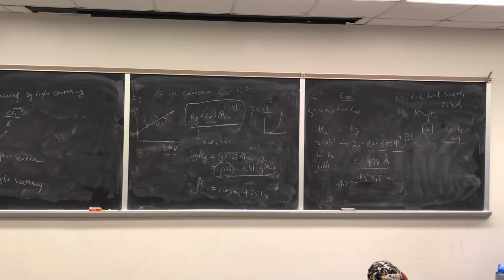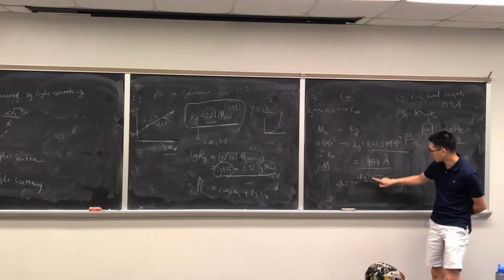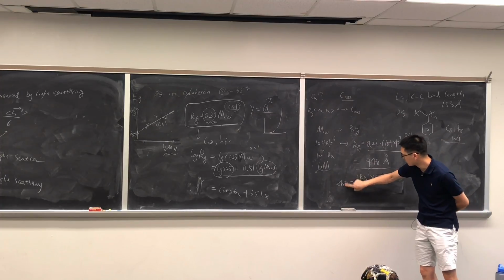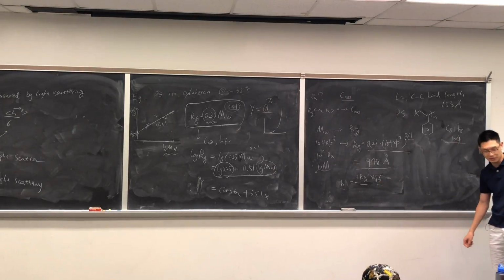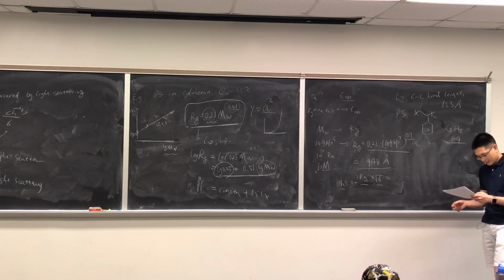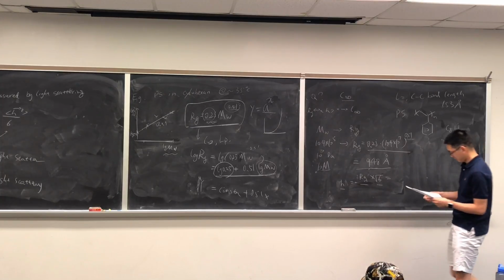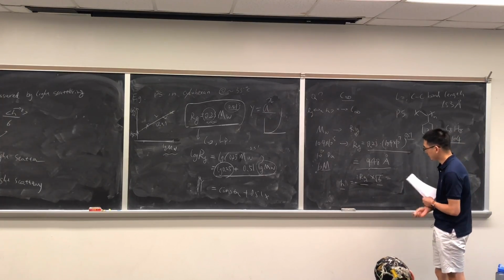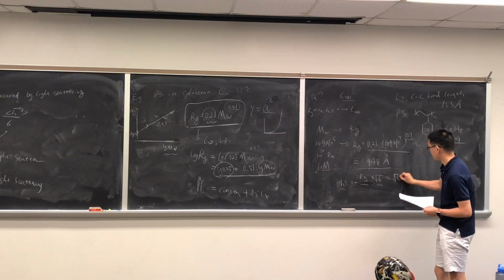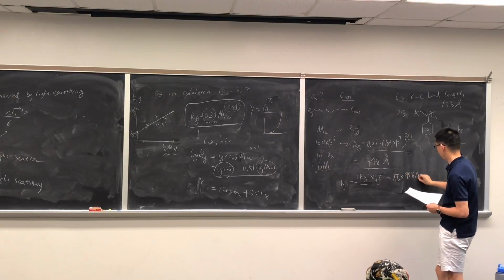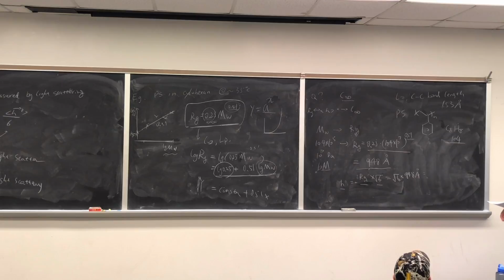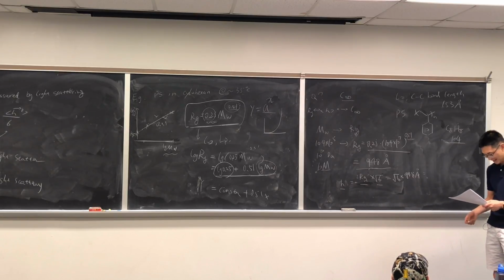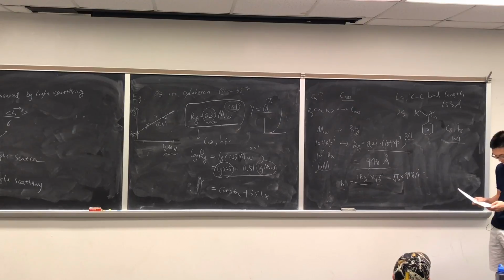So that's what we also learned. How does end-to-end distance relate to RG? For the sake of discussion, I put the bracket for the average, but you can also remove them. We are not deriving the equation. End-to-end distance and RG have this root 6 relationship. So what's next? It will be root 6 multiplied by 948 angstrom, which is 2,322. I didn't calculate that in my notes, but let's say yes, correct.